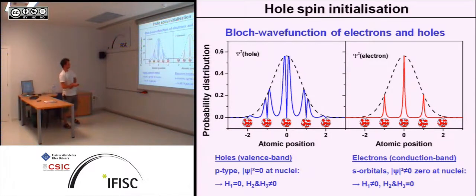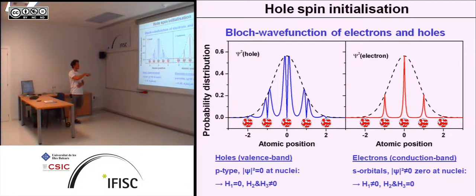Okay, so now to show you why we think holes are interesting and maybe more promising than electrons, you can look at the Bloch wave function. A carrier confined to a quantum dot has an overall symmetry which is dictated by the shape of the quantum dot. We assume a parabolic confinement potential, and this has been fitted by experiments, and it agrees more or less, at least for the lower states in quantum dots. And then you have the symmetry which is called the Bloch wave function, which is dictated by the nuclei or the atoms the quantum dot consists of.